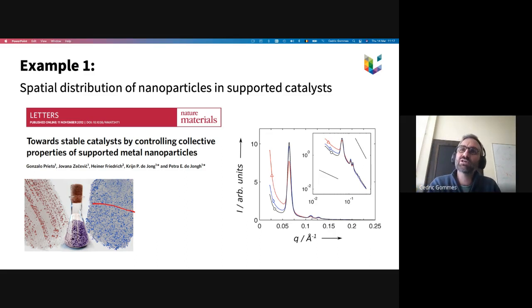And this is a scattering pattern of these materials here. This is the scattered intensity as a function of this quantity, which is basically proportional to the angle. So you have this sharp peak here, which comes from the fact that this has an ordered pore structure, but the information is in this background here. This diffuse background characterizes the spatial distribution of the particles inside these pores.